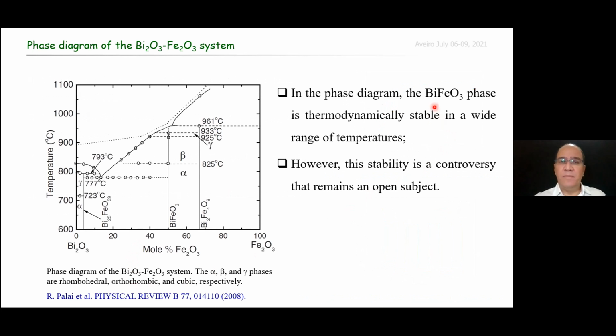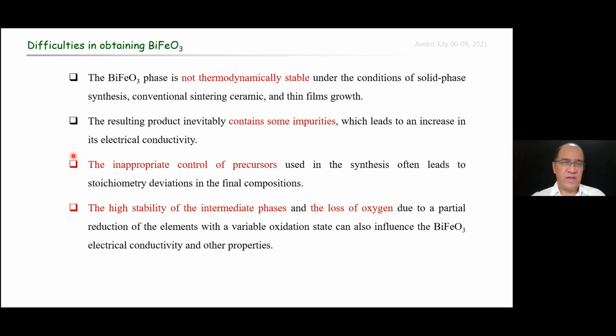In principle, the BiFeO3 phase is thermodynamically stable in a wide range of temperatures, as we can see in this phase diagram of the bismuth oxide, iron oxide system. However, this stability is a controversy in the literature that remains an open subject. Despite this controversy, more and more evidence has indicated that bismuth ferrite is not thermodynamically stable. It is one of the most critical difficulties in obtaining the BiFeO3 phase.